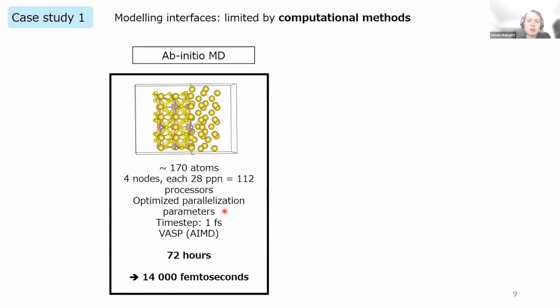We have optimized the parallelization parameters, so that's with kpar and ncore, for example. For a time step of 1 femtosecond, it took 72 hours, that's a wall time, to only get a simulation of 14,000 femtoseconds, so 14 picoseconds. That's an extremely short time, especially for a very small system, when in reality, you really want to study much larger systems when you're looking at battery materials.